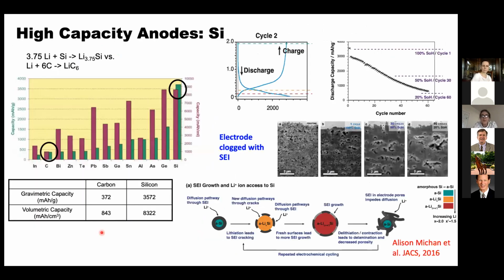about where we're using our in situ NMR. And the first one we did was to really use the NMR to look at silicon. And silicon is the material that people are excited by because in principle, if you could use silicon instead of graphite, you could get 10 times the gravimetric capacity, or also 10 times the volumetric capacity. And sometimes you care about volumetric capacities, sometimes gravimetric, depending on whether, for example, it's a drone or an aeroplane, or this is a laptop or a car where you might be more concerned about the volumetric energy density.